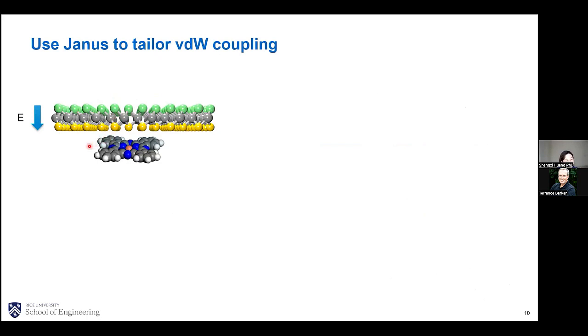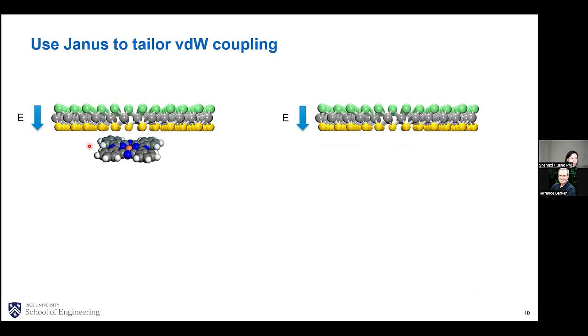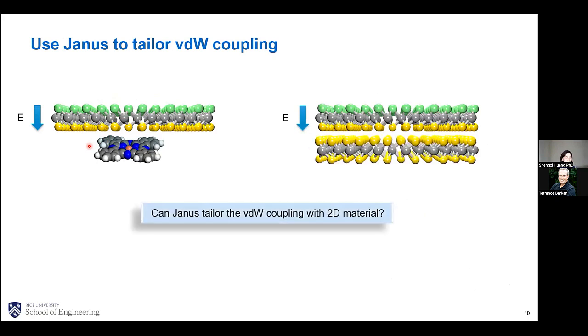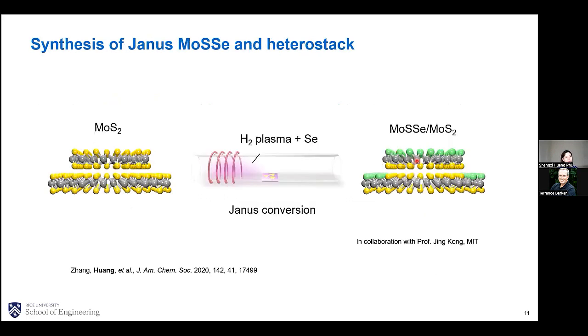So before I study this system, let's just look at a cleaner system. So instead of putting a molecule, I will just put another layer of 2D material on the surface. So now the question becomes, can Janus tailor the van der Waals coupling with 2D materials? Well, in order to study this system, let's first synthesize this material. So we collaborated with Professor Jing Kong's group at MIT, and we synthesized these Janus MoSSe layers and their heterostacks.